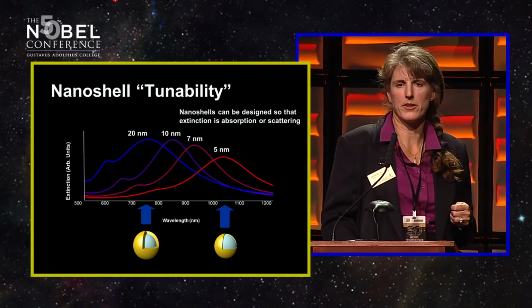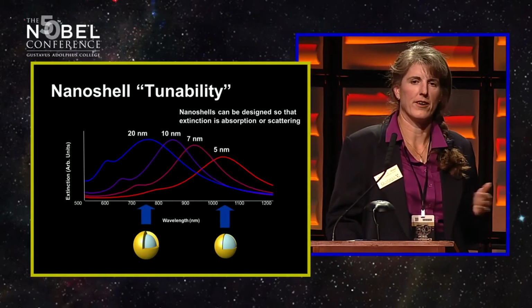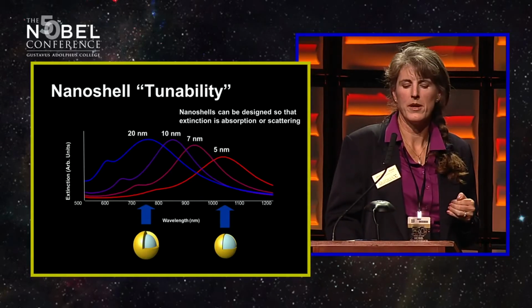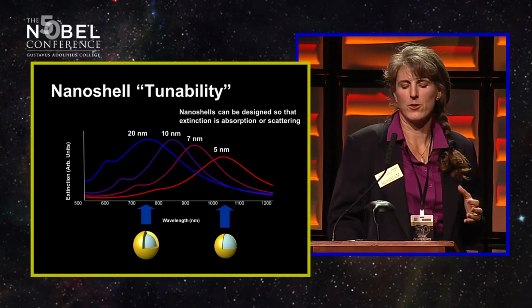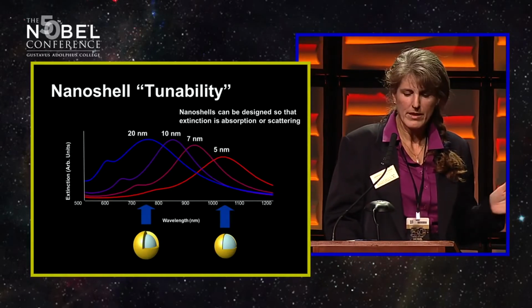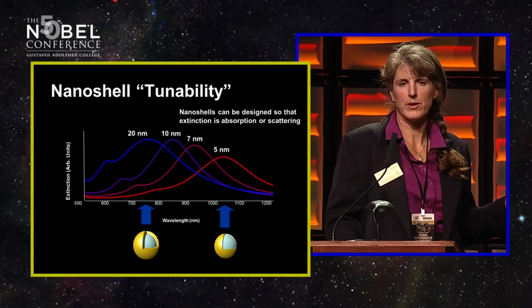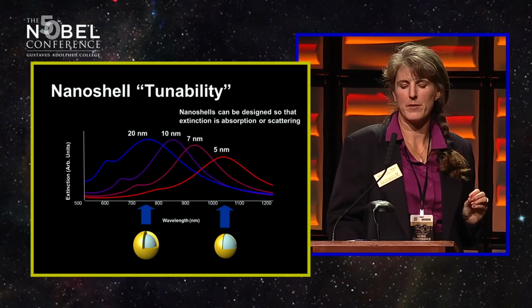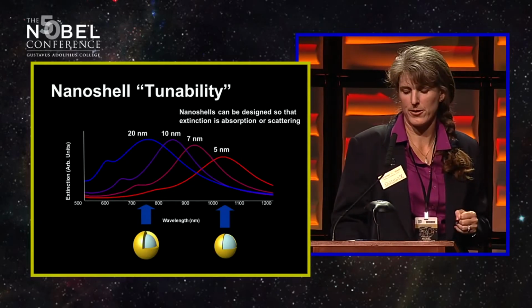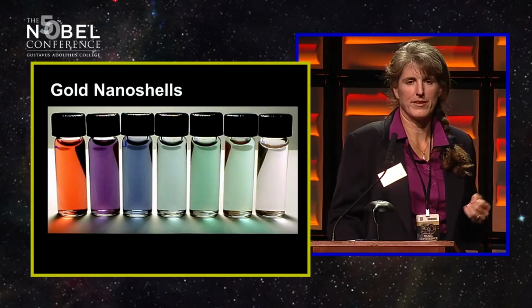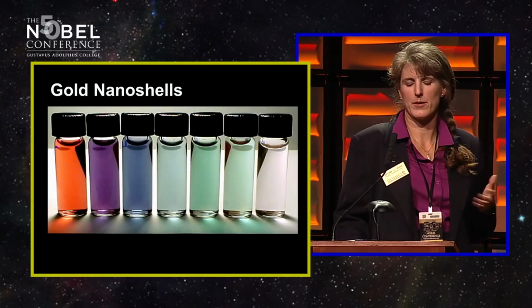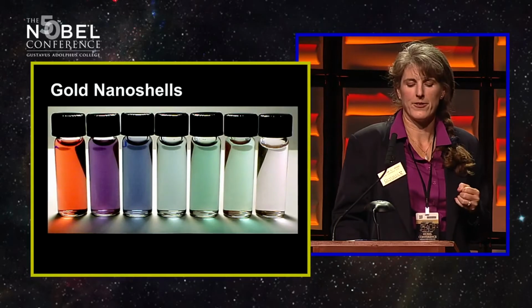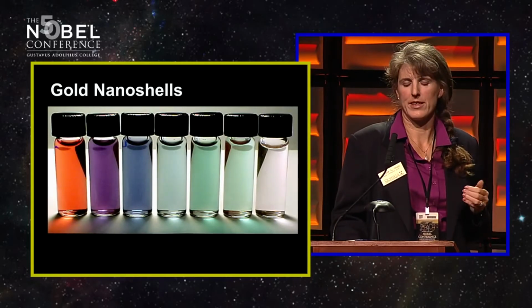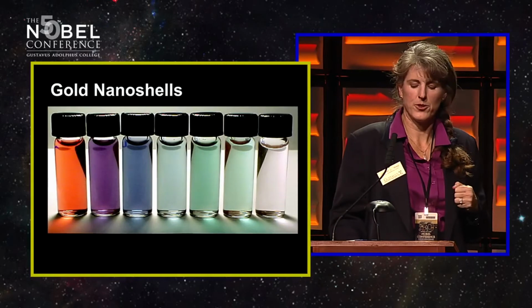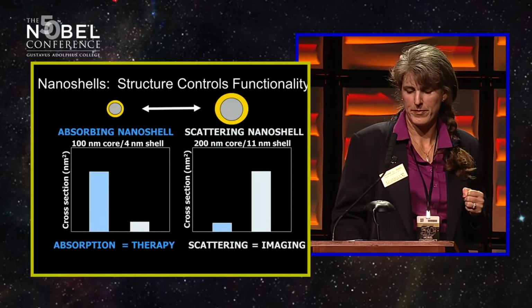This is an example looking at 4 batches of nanoshells that all had the same size silica cores, but different thicknesses of gold shell on the outside. You can see as we go from a 20 nanometer thick shell down to a 5 nanometer thick shell, we're moving where the peak for absorption of light is occurring. Sometimes it's easier to look at samples, so this is a similar set of samples where, going from left to right, you're getting progressively thinner shells. You can see that we're tuning the color of the particles.